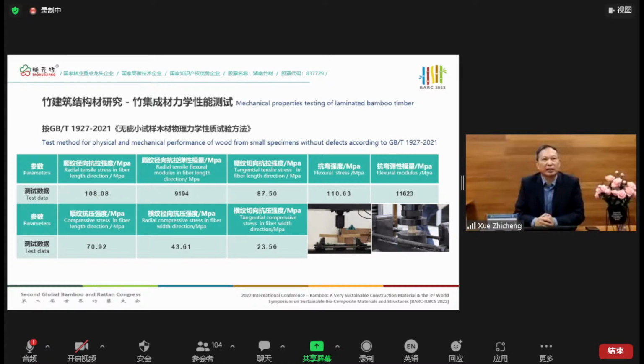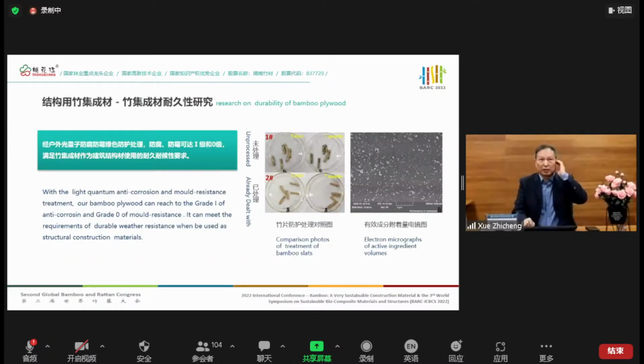We also had the testing of properties, tangential tensile strengths and radial tensile flexural modulus, radial tensile stress, as shown on this table. Some data, very good testing results, showing that the laminated bamboo has good mechanical properties and can meet the national structural standards. We are following the GB 1927-2021 test method for the physical and mechanical performance of wood from small specimens without defects.